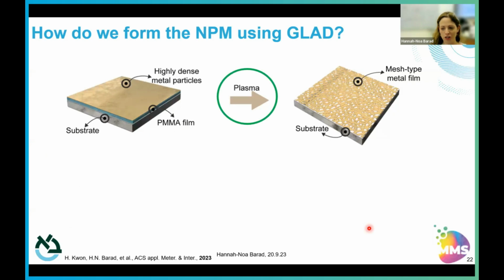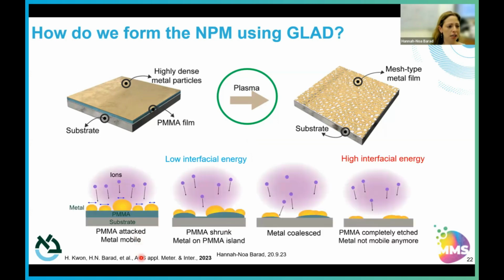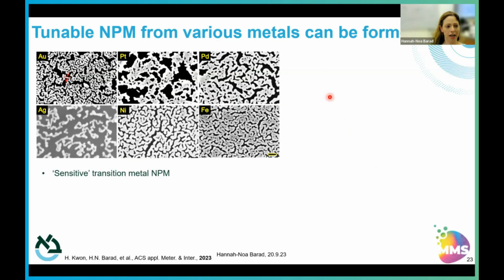What is in fact happening, and more interesting, is the plasma aspect. This plasma effect, I'm not going to go deeply into the mechanism over here, but it pretty much involves the initial stage where we have the ions that start attacking the PMMA and of course reducing it. At this point, the metals become a little bit mobile due to some internal thermal effects and the movement and etching of the PMMA. And because we have low interfacial energy between our metal nanoparticles and the PMMA, the PMMA shrinks, but the metals also shrink together with it, forming islands. Then eventually the metals start coalescing. The PMMA is completely removed. At this point, we have high interfacial energy between our silicon substrate and our metal, so they do not move anymore, and they actually form these nanostructures. And what's nice about this is that we can really do pretty much any metal that we want.